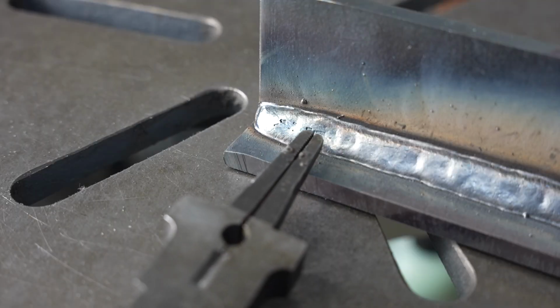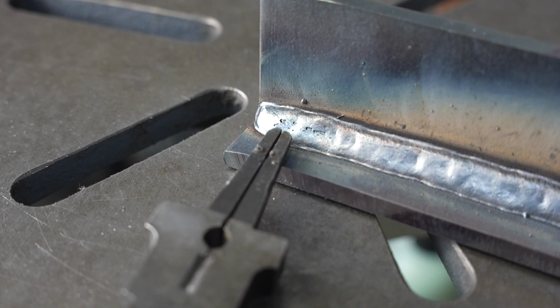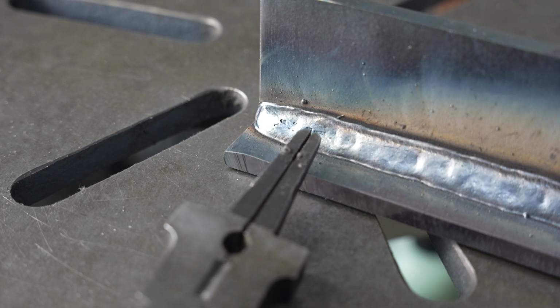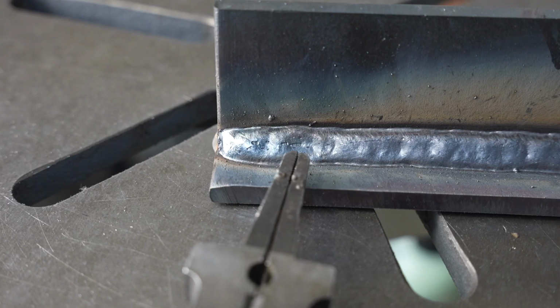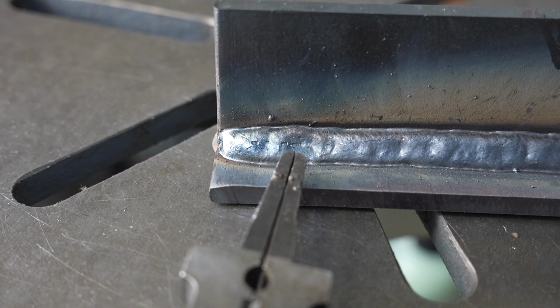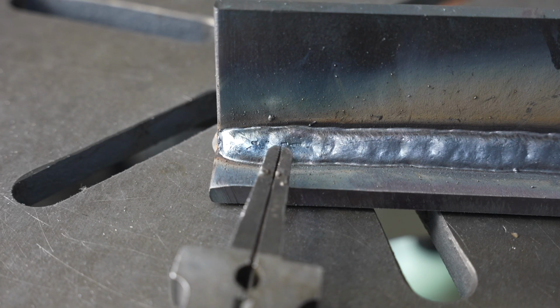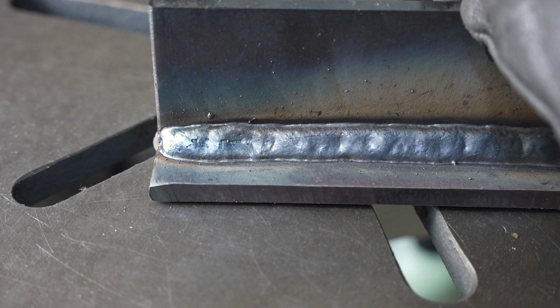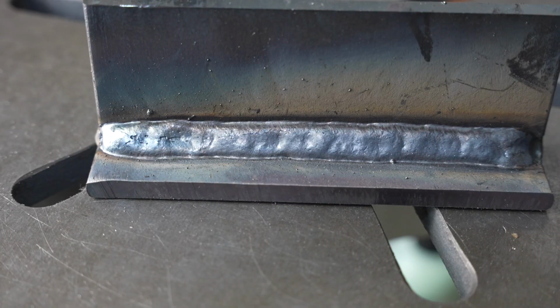So let me show you something here at the start of this weld. Those are worm tracks, and that's where gas was not able to escape out from under the flux in time. And so you end up with those little discontinuities there. Usually they're pretty surface level, but the main reason that this happens is if you're using too short of a stick out. If your wire doesn't have some length to it, it can't preheat on the way in. So if you hold a longer stick out, it's a lot better. Notice the rest of this weld is completely clean.